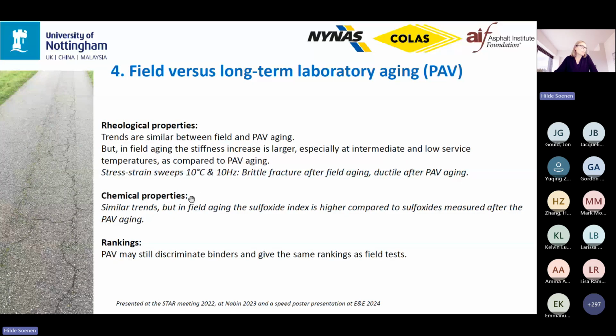Regarding the chemical properties, we also noted some differences. There are much more sulfoxides in field-aged samples compared to the sulfoxides you see after the pressure aging vessel. And regarding the rankings, we had 2 binders for which we still had the original samples, but these 2 binders were from the same origin. So unfortunately, we cannot say whether the pressure aging vessel can still discriminate the binders regarding the ranking that they would have in the field. So no conclusion on this last item.